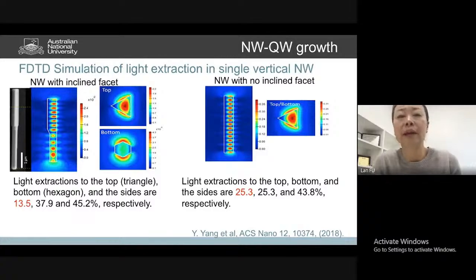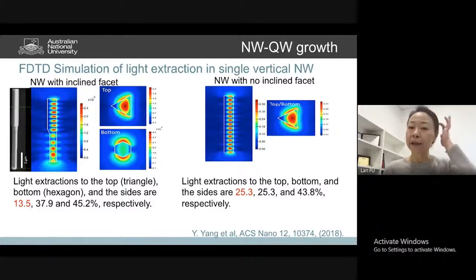Of course, as I mentioned, light extraction is one of the quite important things. We would like to use the nanowire array to achieve good light extraction. So we know that our nanowire has a very complex morphology, right? Look at that inclined facet, and if you look at the top, they're actually triangular shape, and the bottom hexagonal shape. So we've done a lot of simulation trying to understand the light absorption properties in this kind of nanowire shape and how the light extraction will be affected by shapes.